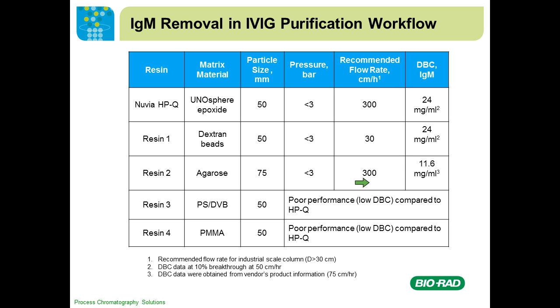Agarose-based beads are rigid, and it's well known that agarose beads are used for size exclusion chromatography. Therefore, you can imagine the pore is relatively small. So when handling a large molecule like IgM, the binding capacity is very limited because the pore is so small. Styrene divinylbenzene often has a large pore, but the problem is the polystyrene divinylbenzene resin itself is very hydrophobic. Although it has been coated with a hydrophilic polymer, it also behaves like some kind of mixed mode, and the recovery is sometimes very low. So the customer considered the performance low.